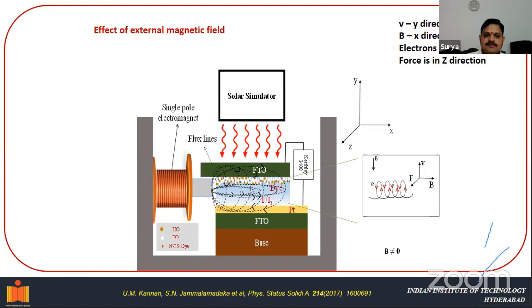One way we achieve this is by transferring the electrons from the singlet state to the triplet state, as the triplet state has a longer lifetime. The second is through the Lorentz force. With the application of both electric and magnetic fields perpendicular to the device, the electron attains a spiral motion, which we call the Lorentz force effect. Due to this effect, the electron spends more time within the device before it recombines. As a result, the efficiency of the device can be enhanced.